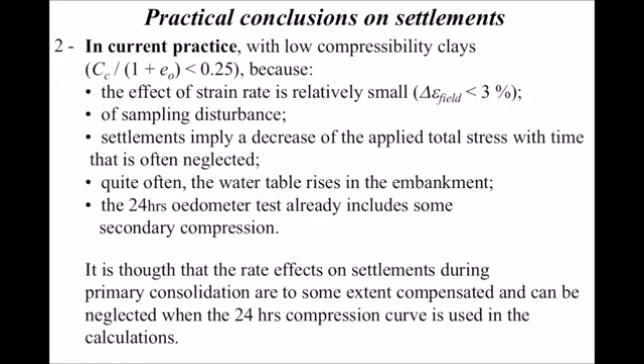for normal everyday practice, low compressibility clays, there are several factors which are fighting against the viscous effects. I mentioned the effect of strain rate first: in low compressibility clays it is relatively small, but in most cases in normal practice, we have sampling disturbance. Settlements imply a decrease of the applied total stress with time that is often neglected. Quite often, the water table rises in the embankment, and the 24 hours oedometer test already includes some secondary compression. All these factors are to some extent compensating for the viscous effects.